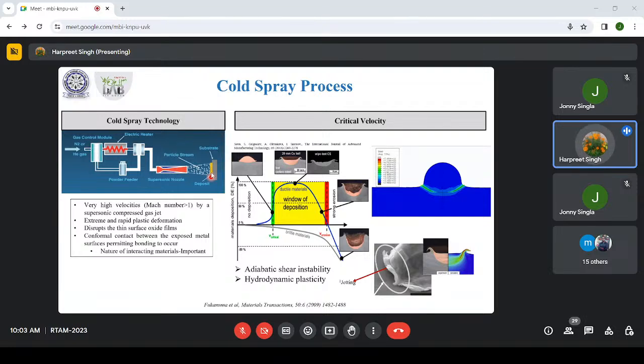So here we have some schematics. We have this electric heater also. From here the gas would come, right? And we have this powder feeder, and we have this electric heater. Now the powder feeder is where you will introduce your powder, and then it will be pushed into the nozzle. This electric heater is basically used to heat the gas mainly. These temperatures of the gas could be up to 1000 degrees Celsius also.